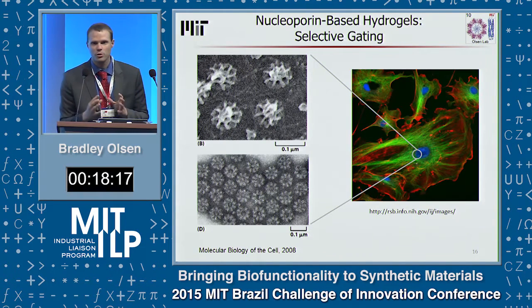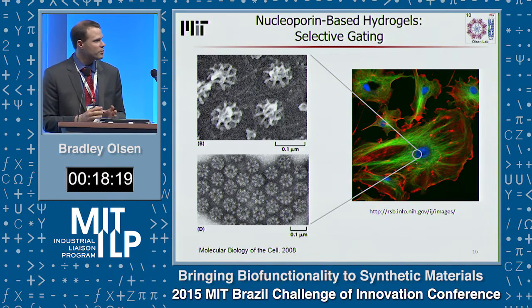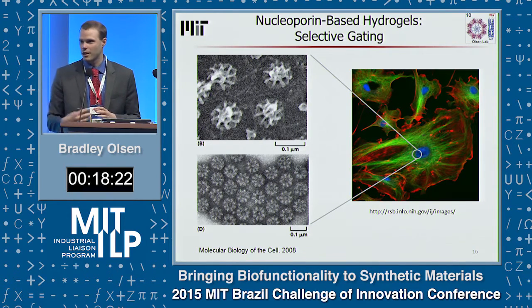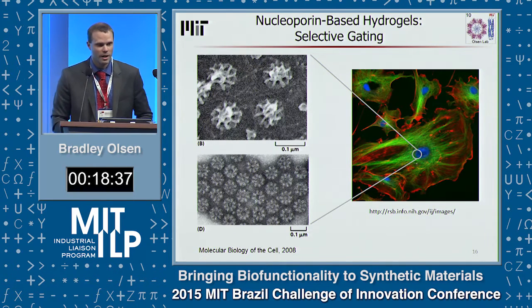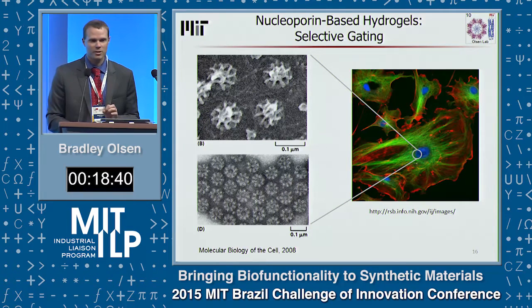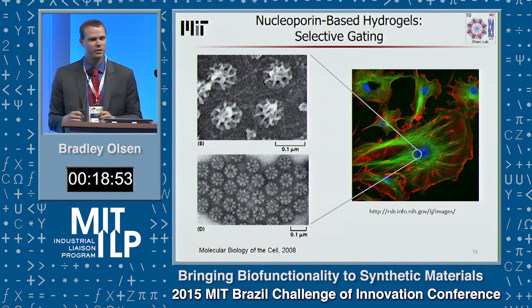And these small pores are critical to your survival as a person, because these pores regulate what gets in and out of your nucleus. So basically, what is allowed to see your DNA, right? So this most precious genetic information is guarded by a hydrogel made of protein inside the pore of your nuclear membrane. And this nuclear membrane is very selective. It allows less than 0.1% of all proteins in your cell to pass through, but it allows translocation per pore of thousands of molecules potentially per second. So it allows very rapid transport of only a few things.